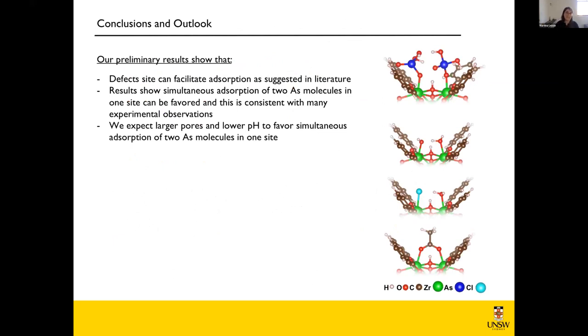So overall, what I showed you is that we can definitely confirm the experimental findings that the defect sites must be playing a big role in arsenic adsorption. We did find that it should be favorable to adsorb 2 arsenic at once in a defect site, which would explain a lot of the experimental observations. And overall, we believe that a lower pH and larger pores should maximize adsorption performance.